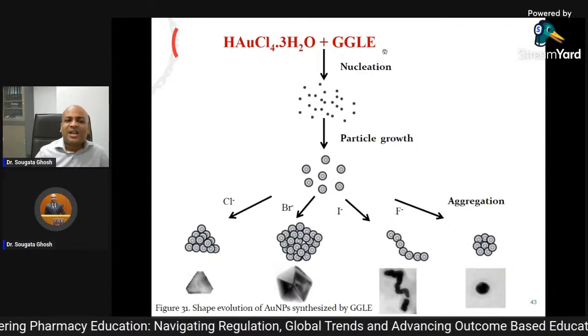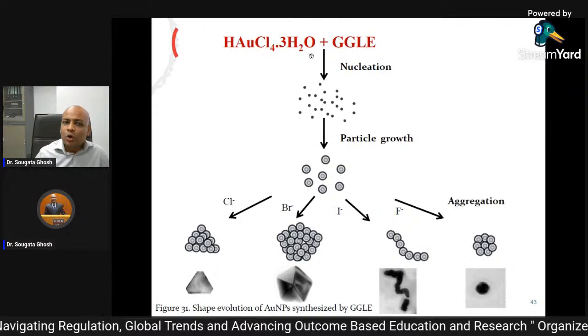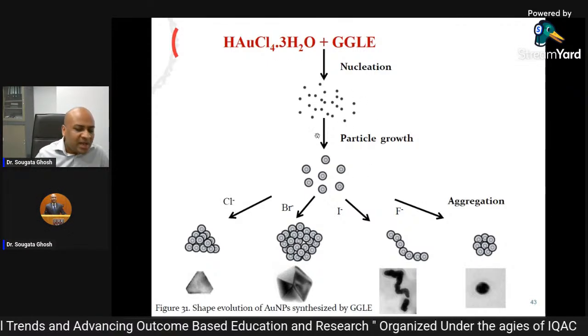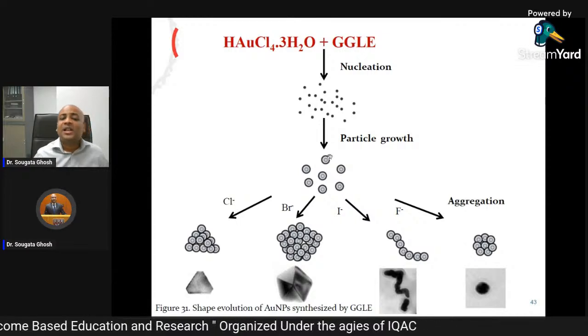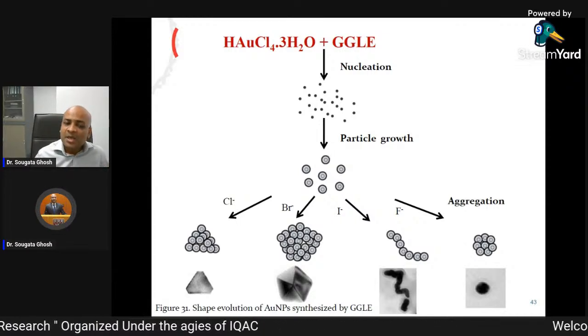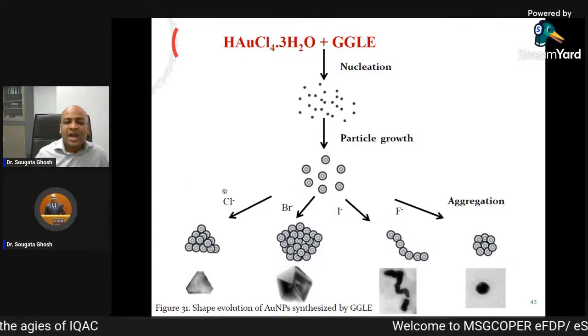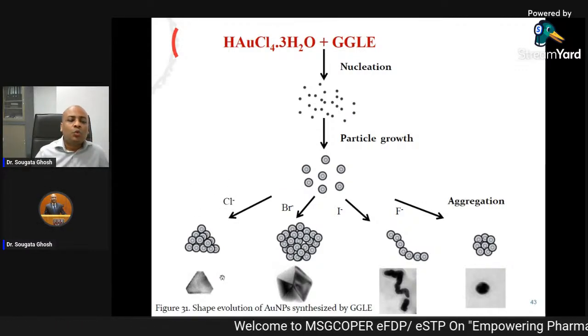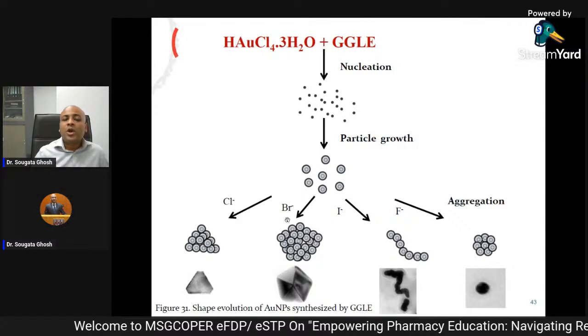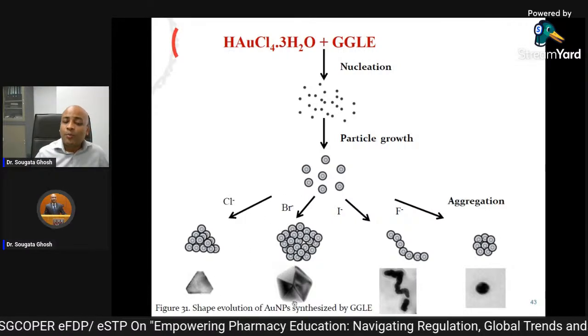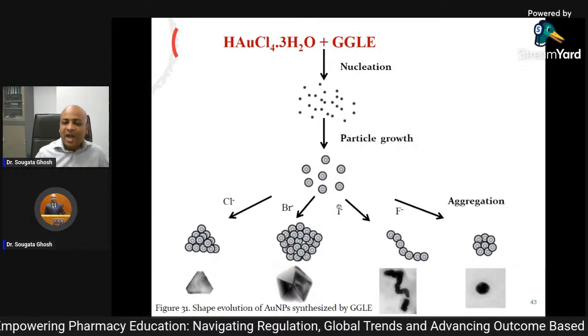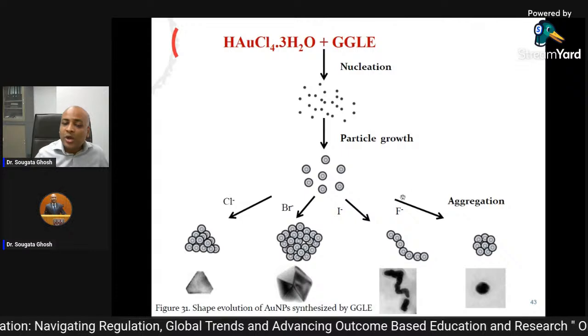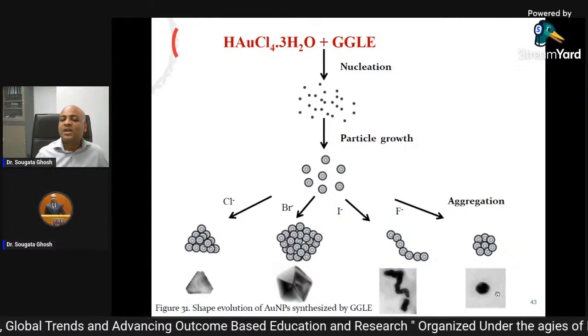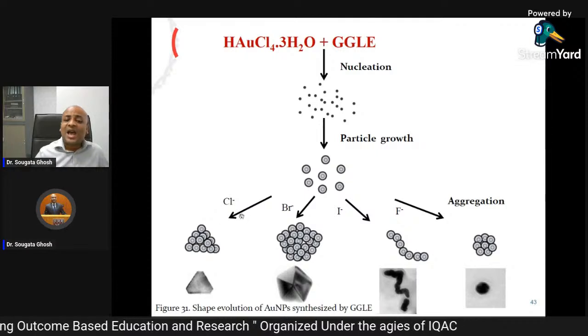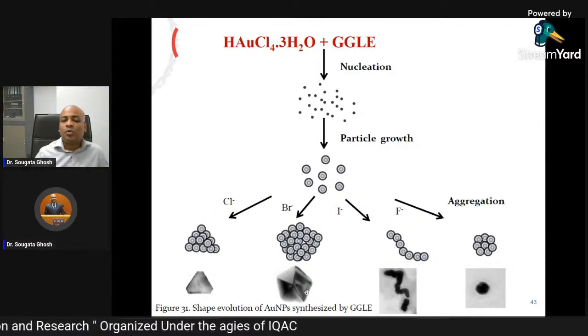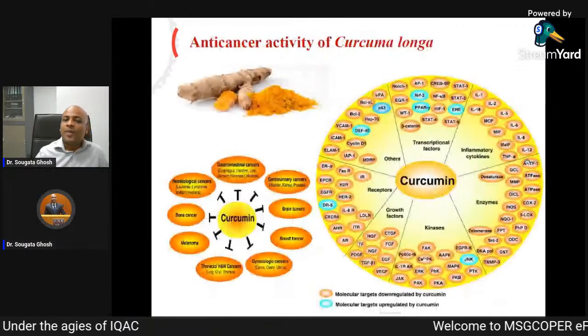As soon as we added the Gnidia glauca leaf extract to gold chloride, there's nucleation. Very small particles are formed. Now these particles come together to form different sizes and shapes. At this point, we added chloride ion. When we added chloride ion, we got nano triangles. When we added bromide ions, we got nanopentagons. When we added iodide ions, we got nanowires. When we added fluoride ions, we got nanospheres. So by changing the halide ions, we could change the morphology of the nanoparticles.